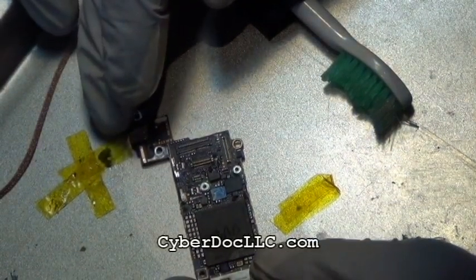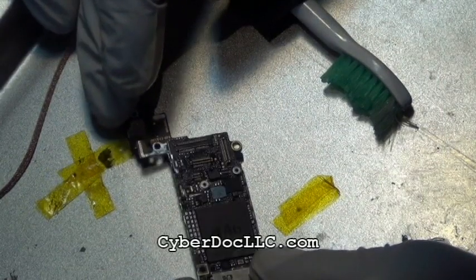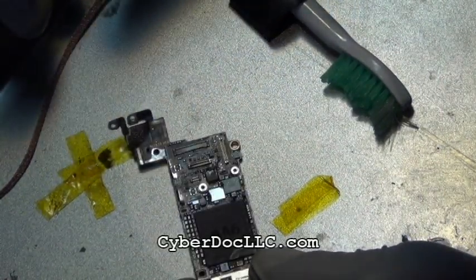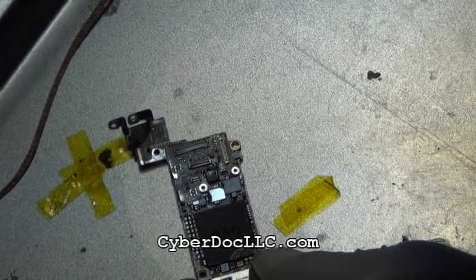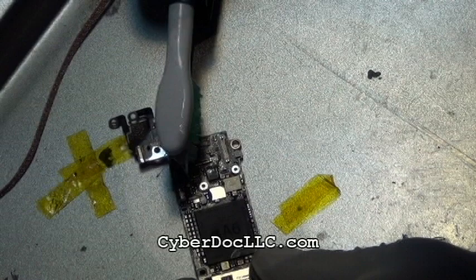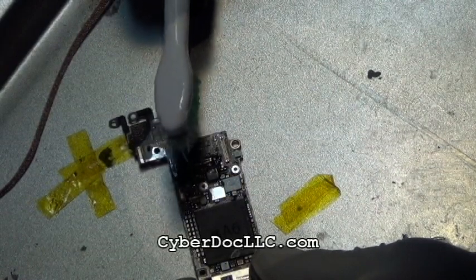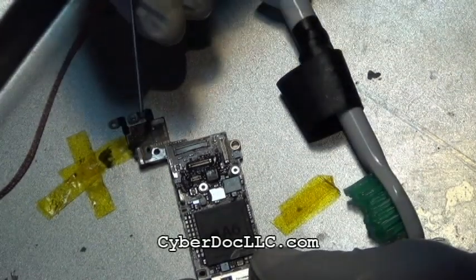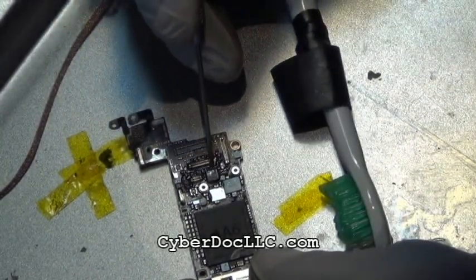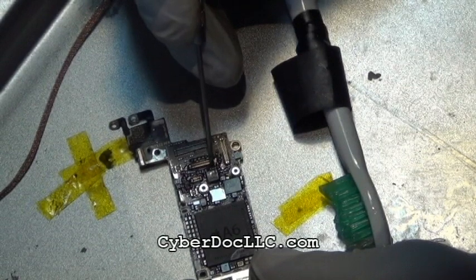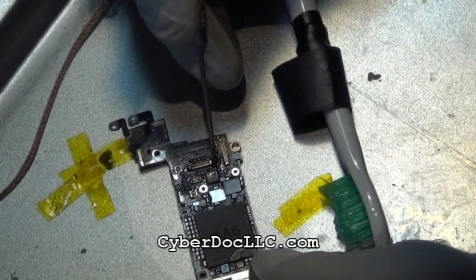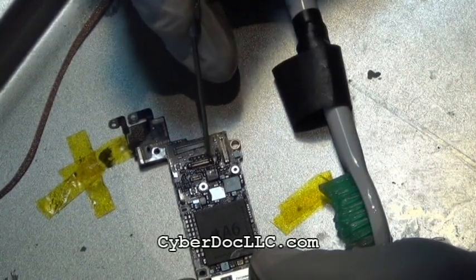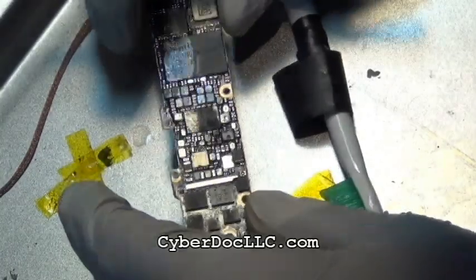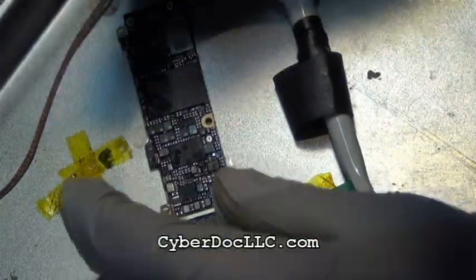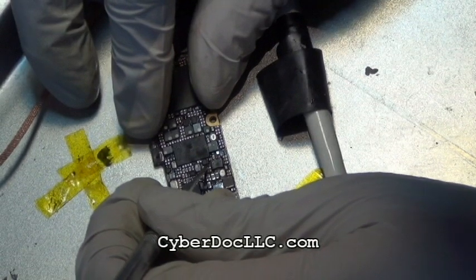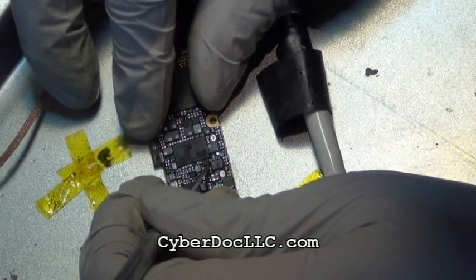Always resupply your flux if your flux runs dry on the board. The flux itself is going to activate the metal. In other words, it's going to deoxidize the metal by the active acid inside. And more importantly in this repair, since the flux I use doesn't have very strong acid in it by definition, because it's no-clean flux, no acid in there, it's just weak acid, the flux is there to conduct heat, to supply equal distribution of the heat to the component you want to solder. So, yeah.